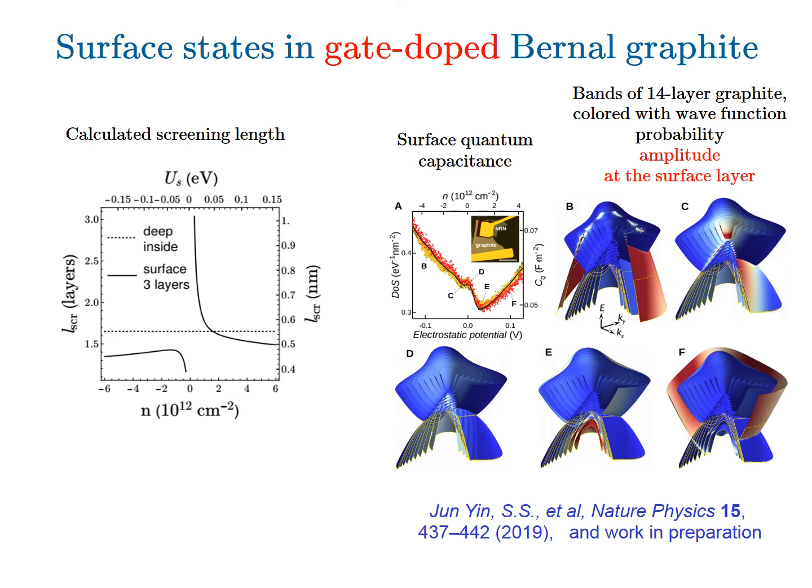An effective penetration depth of the external potential into graphite is approximately 2 layers. The surface states can be viewed as states trapped in the one-dimensional electrostatic potential well near the surface. As usual, with growing depth of the well, more bound states can be trapped near the surface, forming several surface state bands.